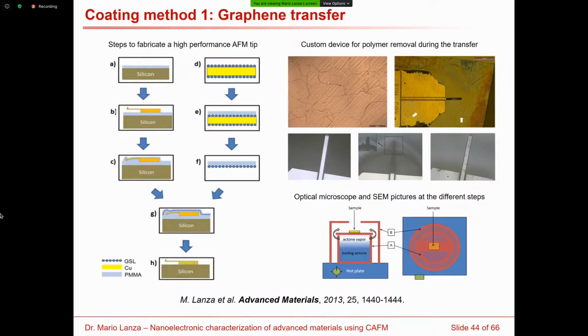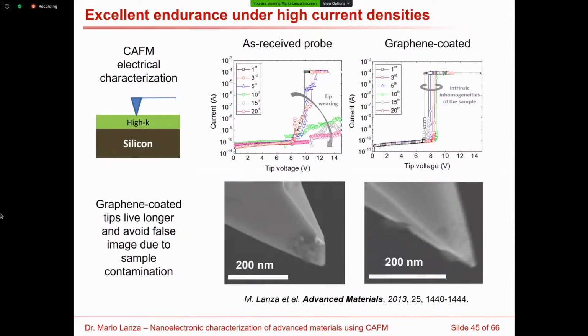And you can see clearly that the cantilever bends when we transfer the PMMA graphene, but after we remove the PMMA, we see that the cantilever recovers the initial position. And we see here some faults which may be related to the presence of graphene. Of course, you don't see the graphene in this optical microscope picture. We took some SEM images, and we also were not able to observe the presence of graphene. However, we did observe that the degradation of the tips on which we coated the graphene was much slower. We could make many more electrical measurements, and after them, we observed that the shape of the tip was preserved.